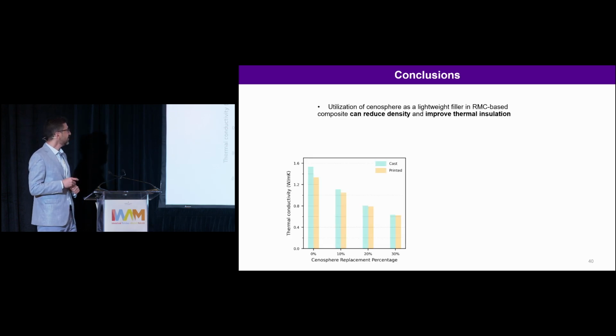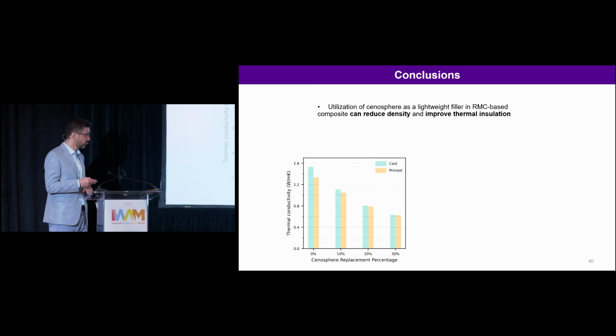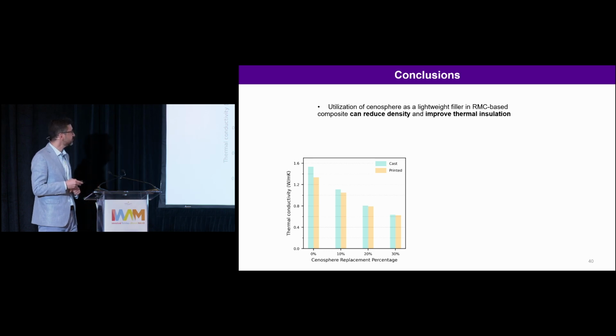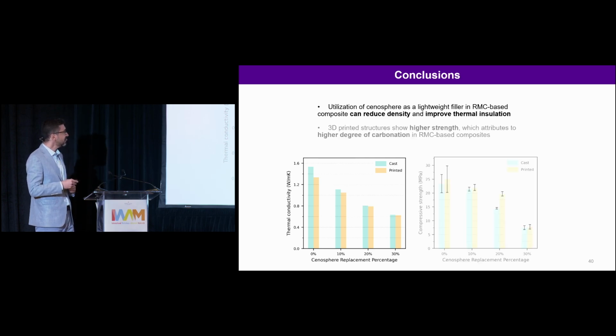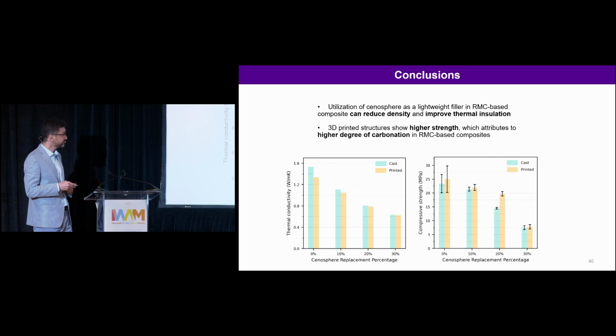And we look at the thermal conductivity. As expected, thermal conductivity decreases with increasing cenospheres, this porous material, and we compare the results with cast and printed versions. Since 3D printing also increased the porosity in the structure, the 3D printed structure has a lower thermal conductivity. And in terms of strength development, the 3D printed structure has larger strength. If you look at this 20% cenosphere replacement, it is because of the carbonation process.